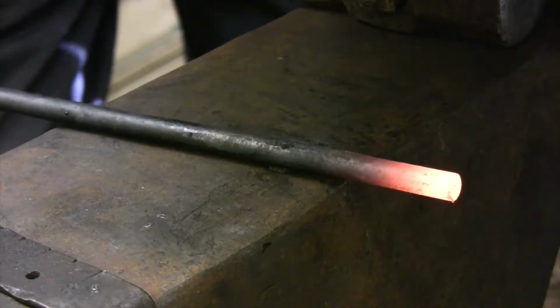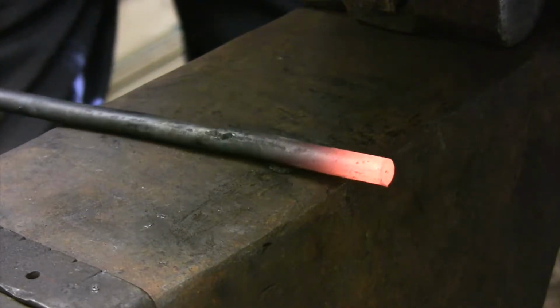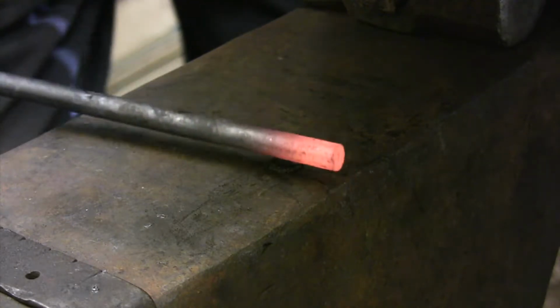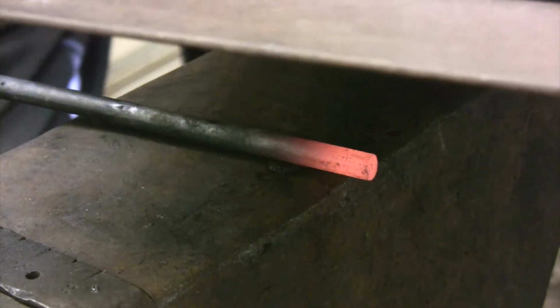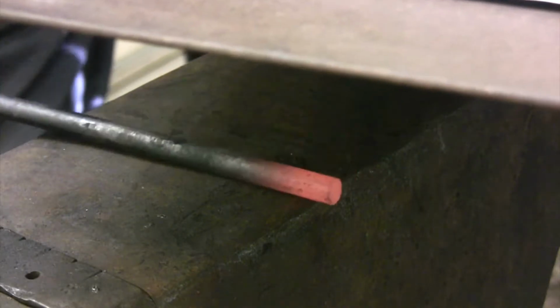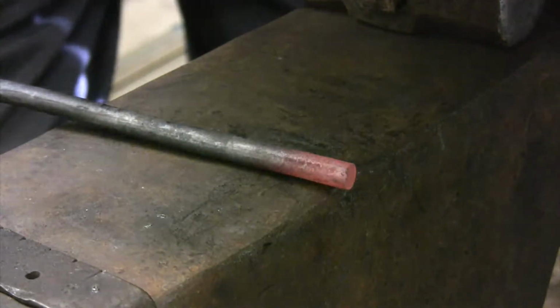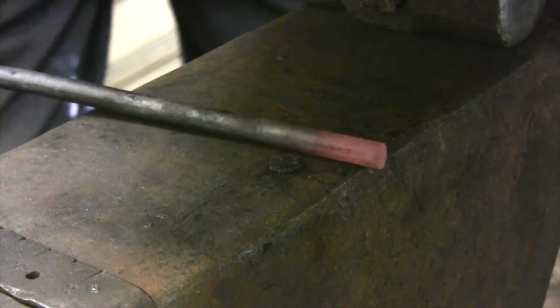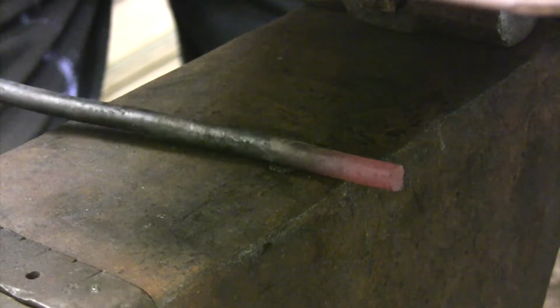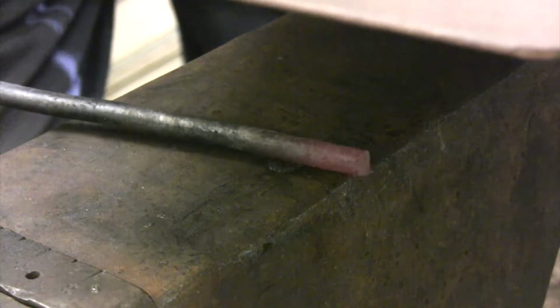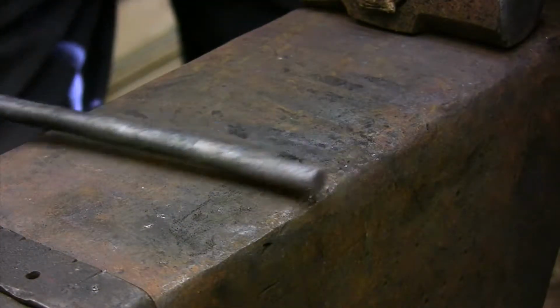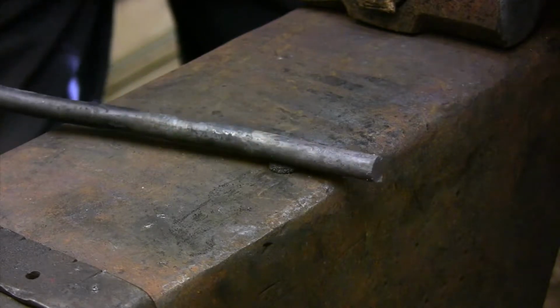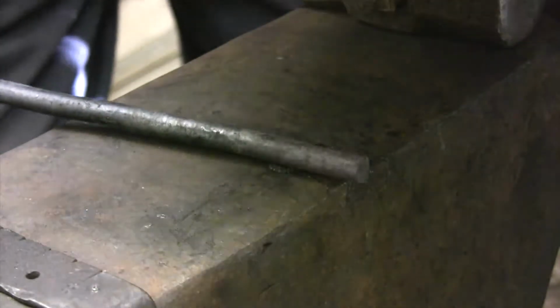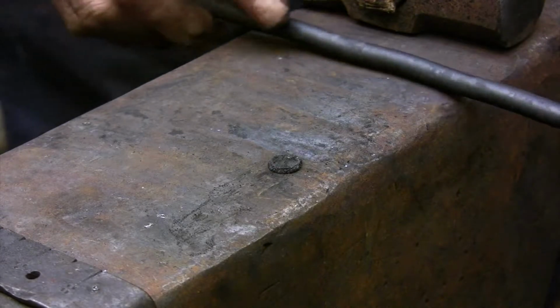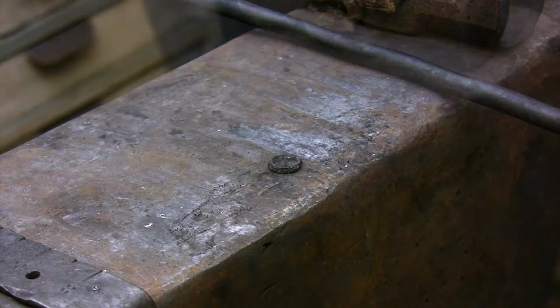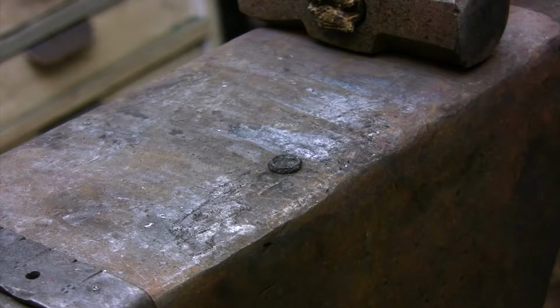The critical temperature for a bar is one of the first things that you need to establish when you're testing a bar that you're not familiar with. At the critical temperature, the bar will no longer be magnetic. This is not a constant, and it actually varies quite a bit, and it all has to do with how the steel is engineered to fit into the customer's manufacturing process. With this piece, it's extremely low. It's becoming non-magnetic right around at a blood red heat, which is barely visible in the shop, so I'm going to need to keep that magnet on the anvil so that I can refer back to it several times while I'm working.